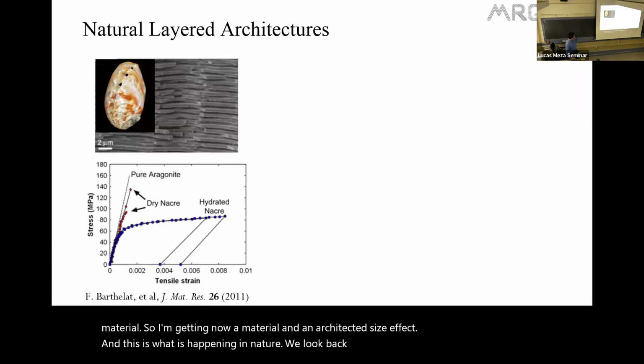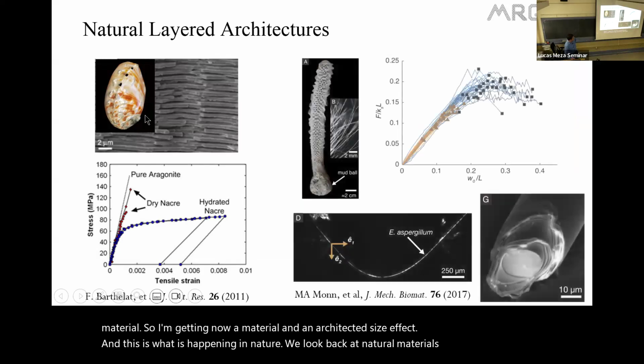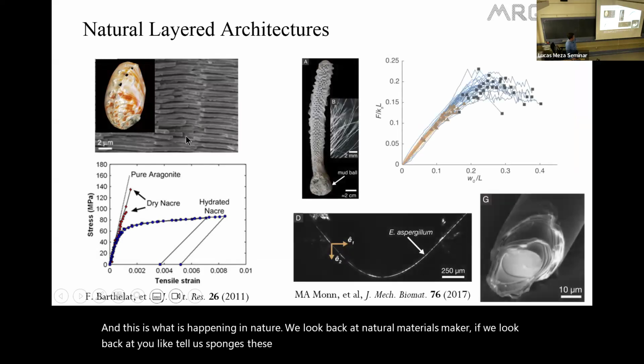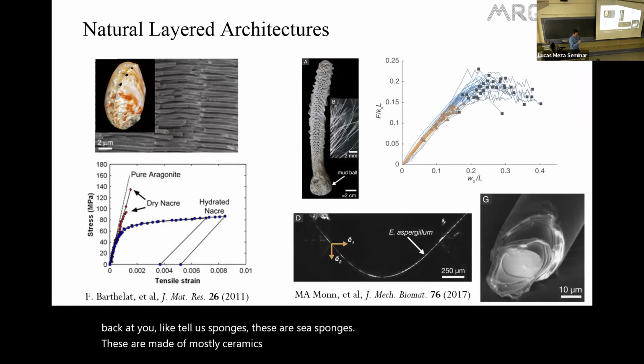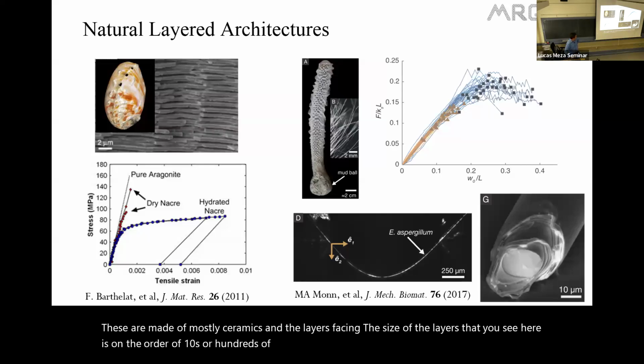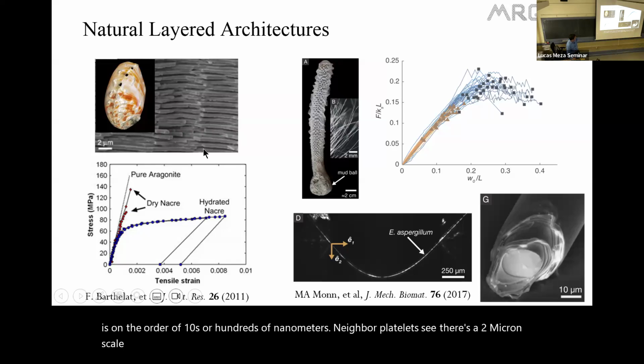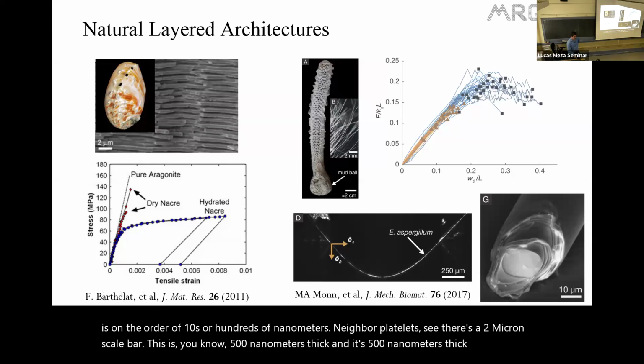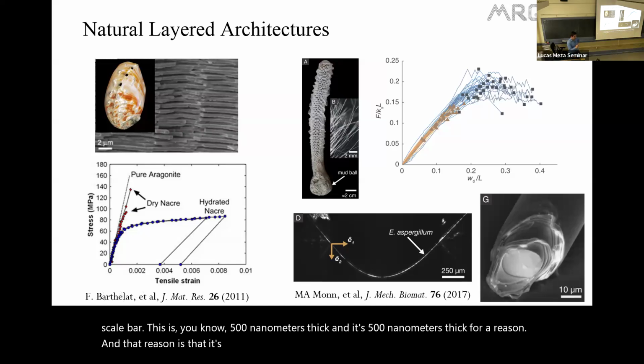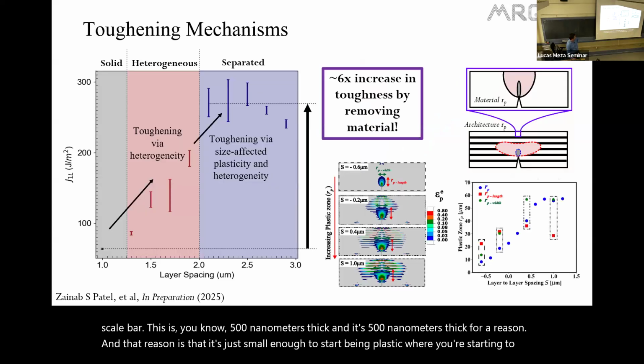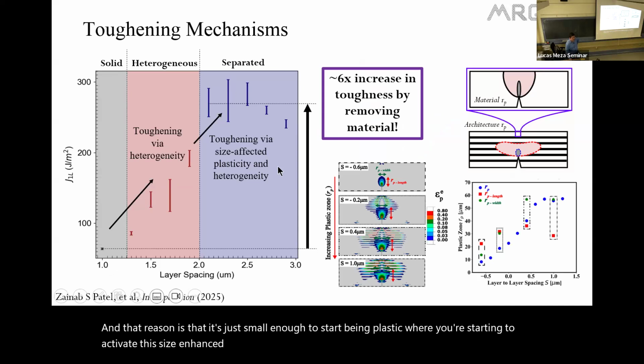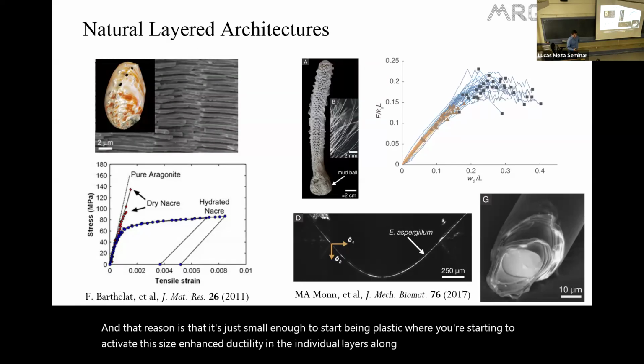If we look back at natural materials, nacre, if we look back at Euplectella sponges, these are sea sponges. These are made of mostly ceramics. And the layer spacing, the size of the layers that you see here, is on the order of tens or hundreds of nanometers. Nacre platelets, you see there's a 2-micron scale bar. This is 500 nanometers thick. And it's 500 nanometers thick for a reason. That reason is that it's just small enough to start being plastic, where you're starting to activate this size-enhanced ductility in the individual layers along with an architected ductility.